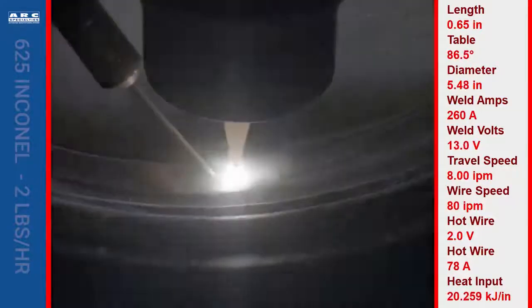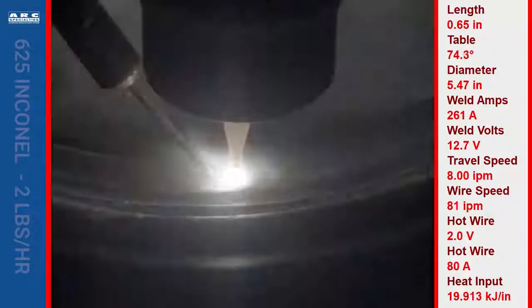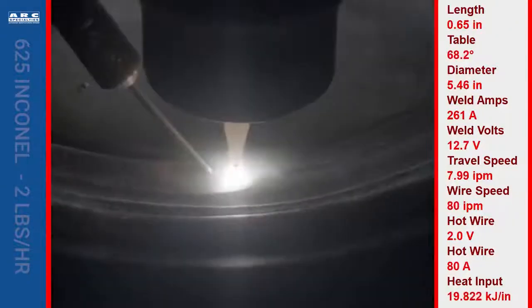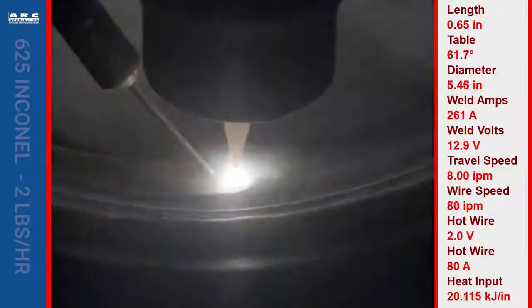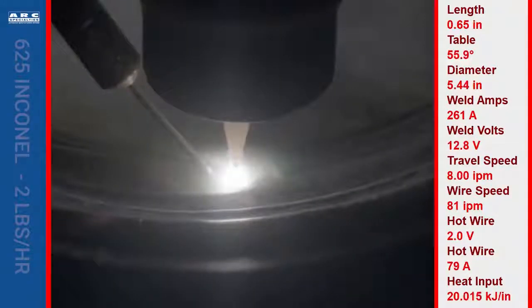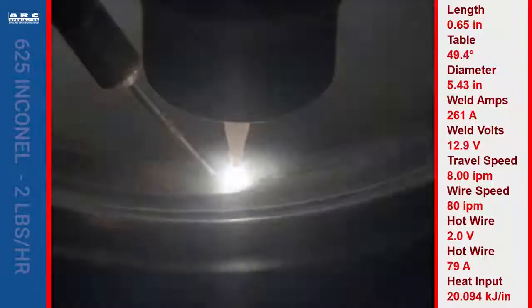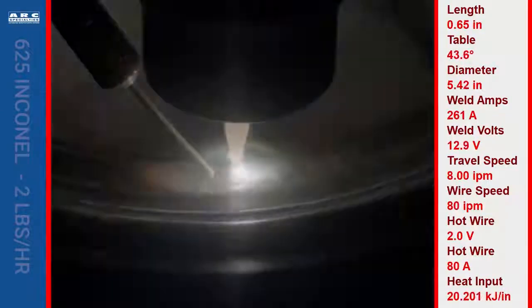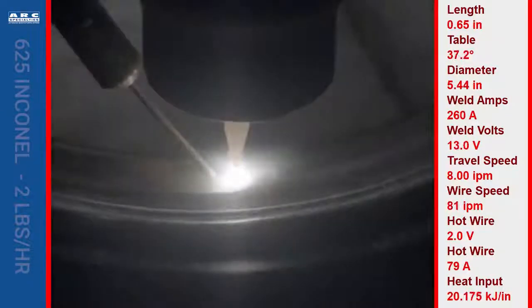Let's talk about arc voltage. This is what controls the length of the arc between the tungsten and the workpiece. Not only is this a key variable for welding, but with hot wire, it introduces another variable. As you increase the arc voltage, the torch moves away from the part, and since the wire is coming in at a steep angle, the wire actually moves closer to the torch.